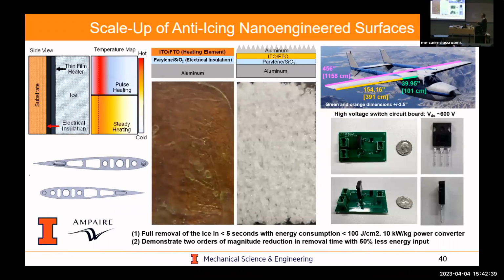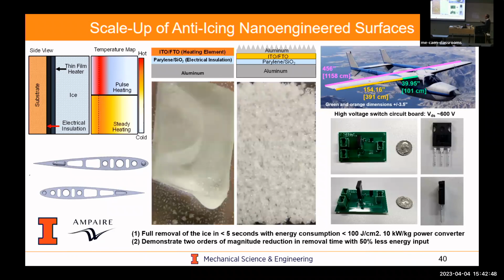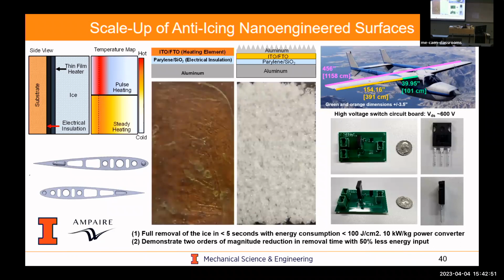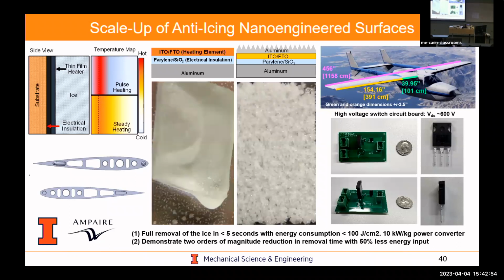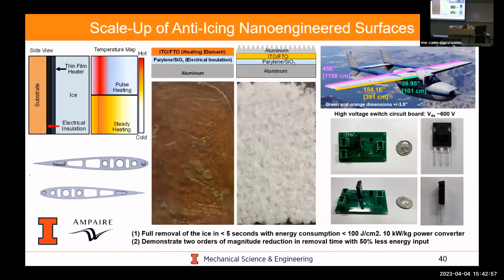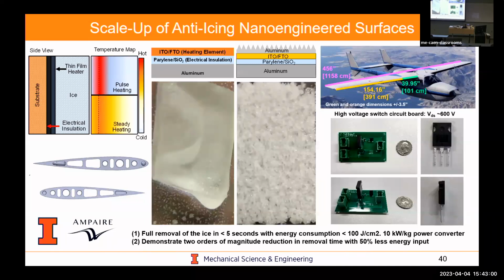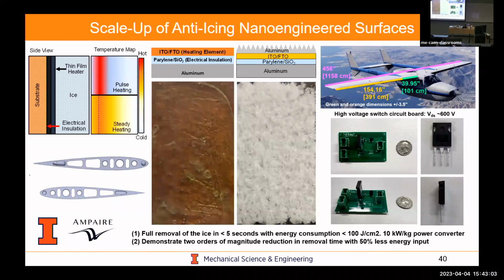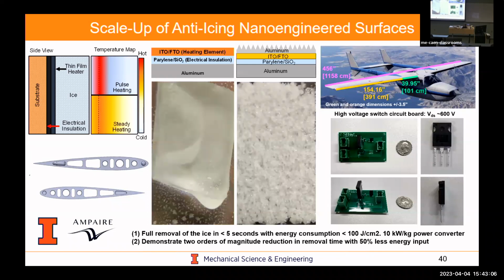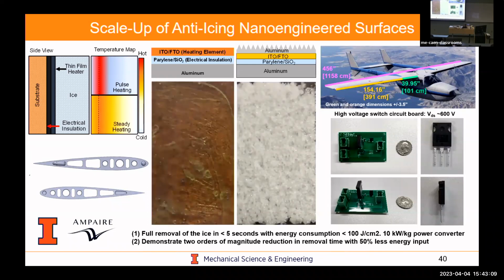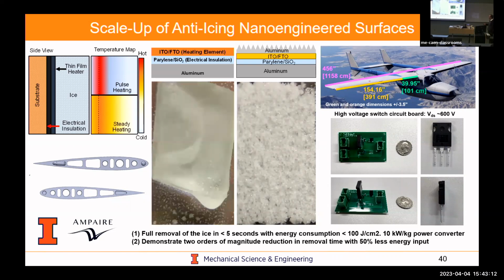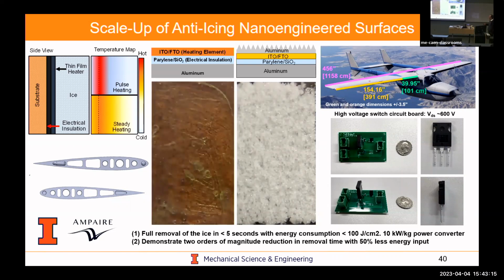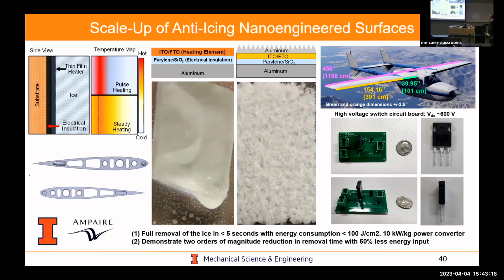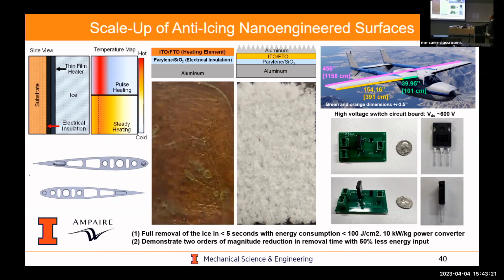And this is actually my last slide. This is another de-icing technology, to show you more fundamental coating-level studies now being applied to real aircraft. This is an electric aircraft de-icing technology, which we call electrothermal pulse de-icing. Essentially, if you have an ice block, beneath the ice block is a coating, parylene, to electrically isolate from the aluminum substrate. And then we have an ITO or an FTO coating on top, which acts as our heater material. By applying a high current pulse instead of a steady heat pulse, you could confine the heat right at the interface. And by doing that, you just locally melt the ice, and you don't have to melt the entire ice layer, and everything will fall off.